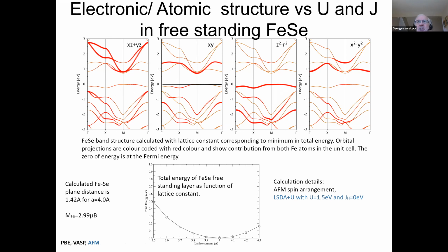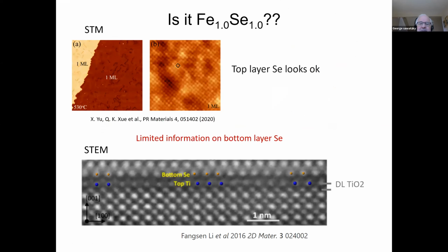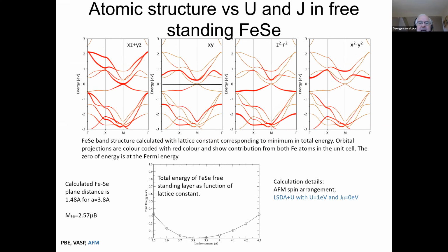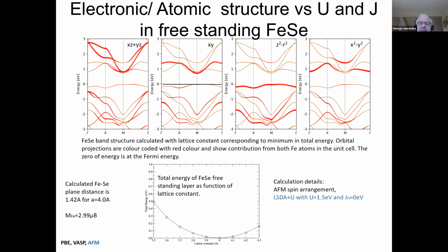And multiplets could cross each other, as they do in the cuprates. They could cross each other relative to what you would get from a density functional calculation, simply because they are multi-Slater determinant states and not single Slater determinant states. Okay, but something like this is going to happen. But what those bands exactly are, we're not sure of actually.